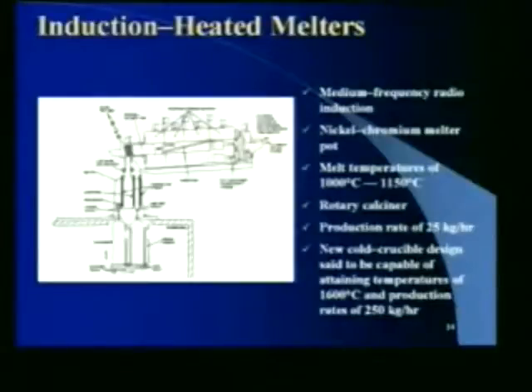Show a couple examples. This is an induction heated melter. And again, I'm sorry if you can't see this very well, but they use medium frequency radio induction, a nickel chromium melter pot, operating in the temperature range of 1,000 to 1150, which means we need glasses that have good properties in this melt temperature range. Typically has a rotary calciner at the top, production rate of about 25 kilograms per hour.